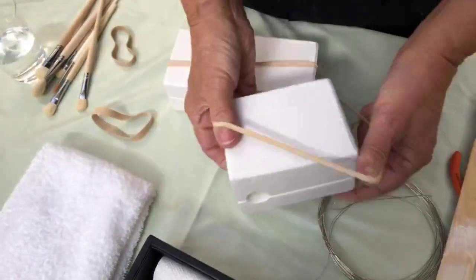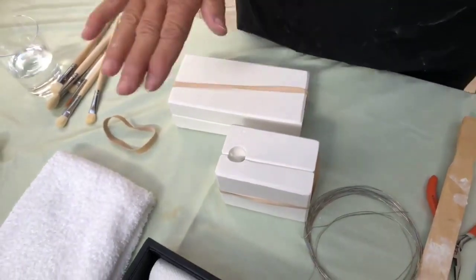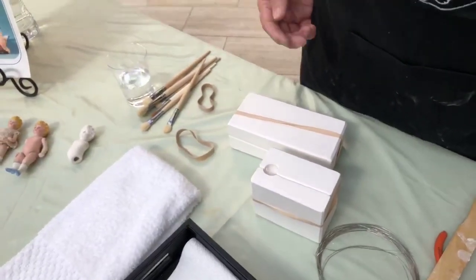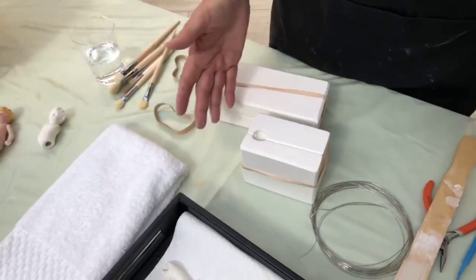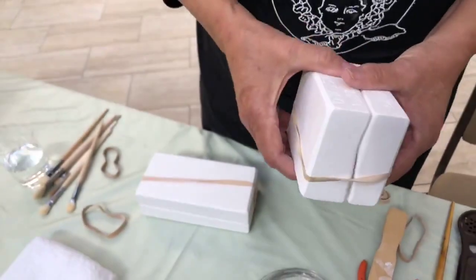This is plaster, and it absorbs the liquid out of the porcelain. It sits for a while, it dries, and then you're able to pour this in, and you let it build up a thickness, and then you pour it out. You let it sit for a little bit because it's like wet clay, like a piece of clay. And so you let it sit until the mold releases, because it pulls the water out of the clay. It probably takes maybe 15 minutes before it'll come apart.